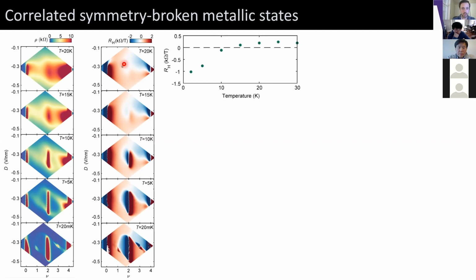And if I were to just track the Hall resistivity at a fixed point slightly away from half filling, you can see that we're actually able to change the sign of it simply by cooling the system down. So again, we think that this means that this region in blue corresponds to what we would expect the sign of the Hall coefficient to be from a single particle model. And this region in green is the opposite of that. So we think the green indicates some sort of spontaneous symmetry broken region.